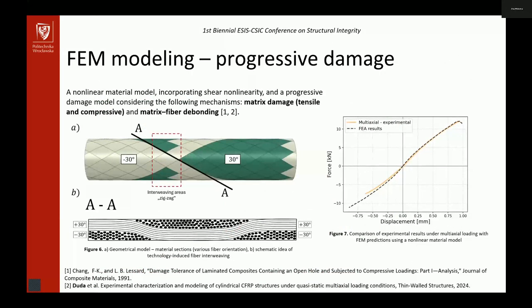Okay, so simultaneously with the static experimental campaign, I developed a numerical model which was used for stress and strain analysis. You can see that if we consider such a structure manufactured by the filament winding method, we have a very specific pattern generated due to the technology, called the zigzag area, where there is fiber undulation, and there is a cross section of this part. This is the red box here.